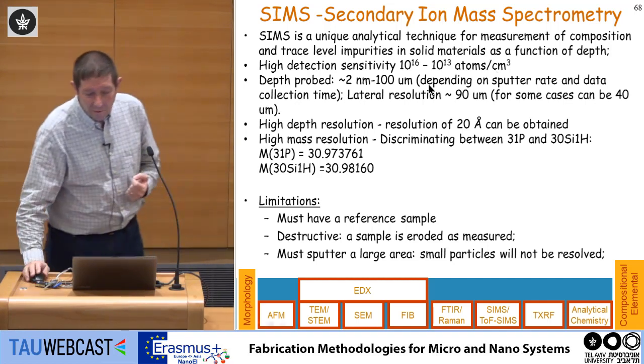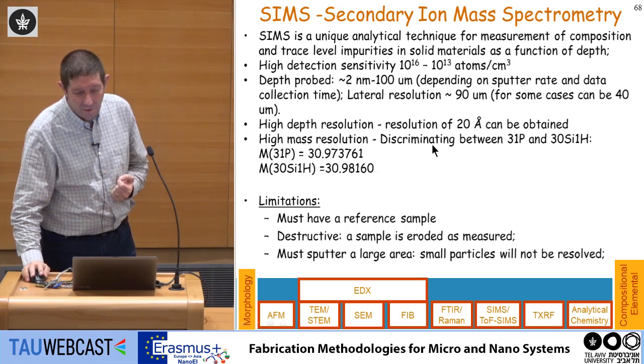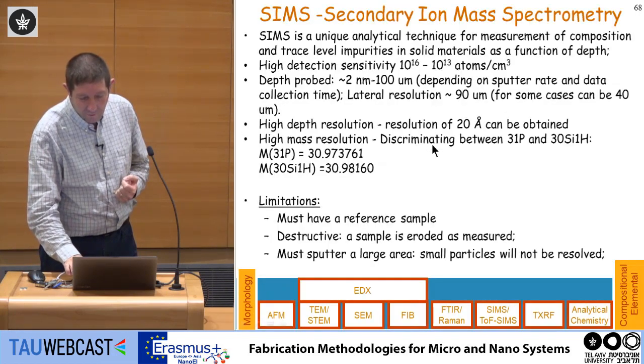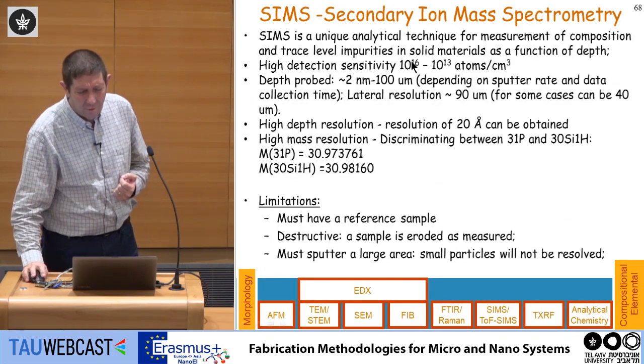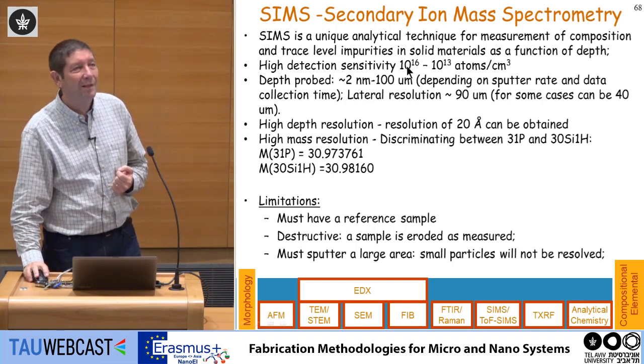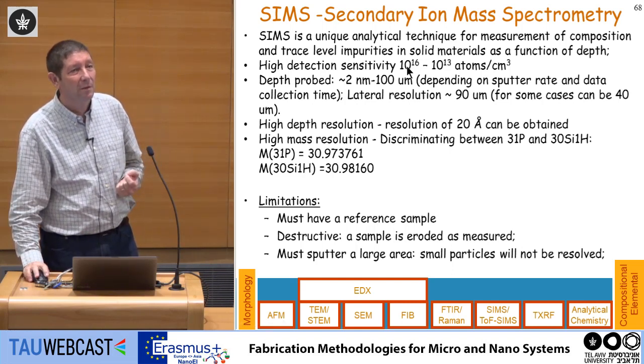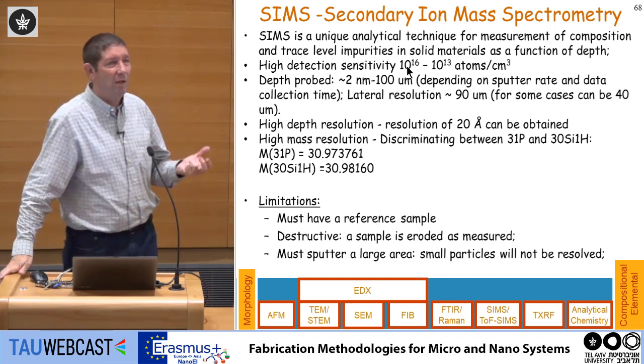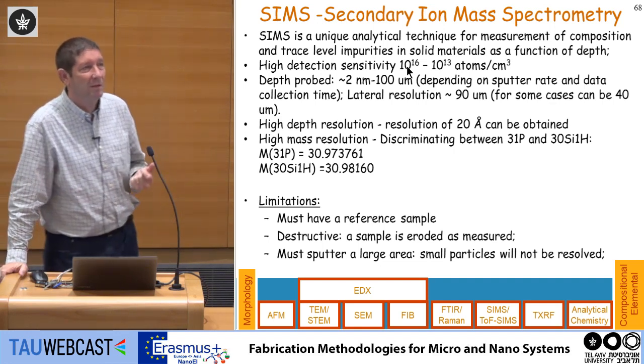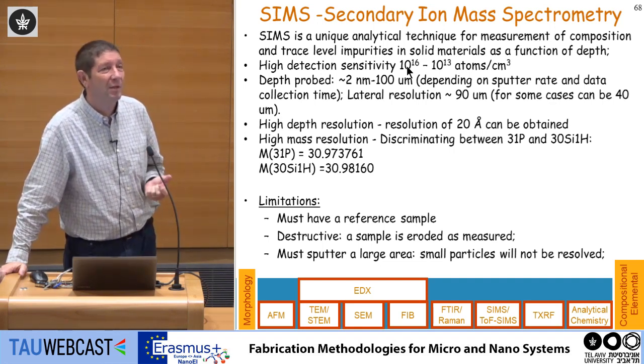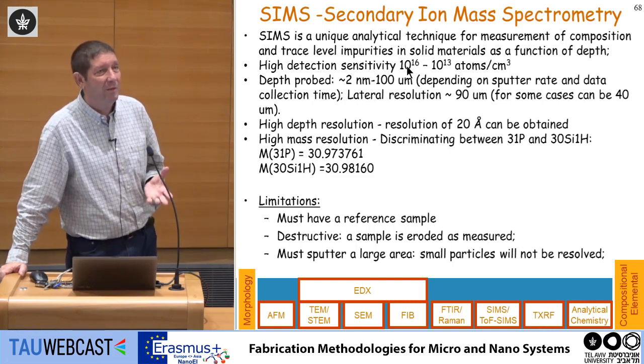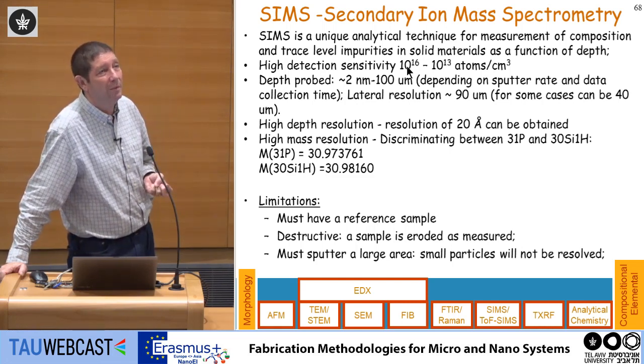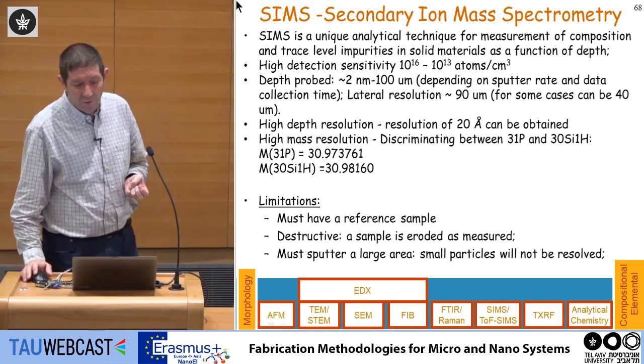If I can detect 10 to the 13, which is really amazing, but usually maybe 10 to the 16, you're talking about parts per million. If you remember, in Auger and XPS and the previous techniques, like EDS, I can detect 1%, 0.1%. Here I can go down to parts per million. So it's a much, much more sensitive technique.